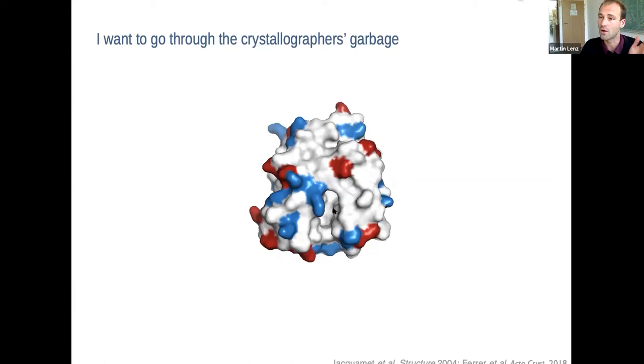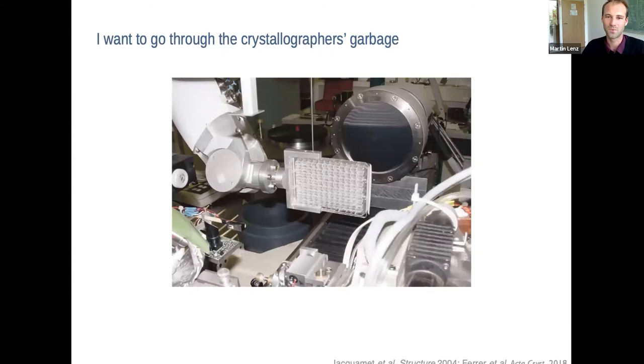And they try to crystallize them with depleting agents, salts, surfactants, relatively mild aggregation conditions, because they want to get a nice crystal. If you push them too strongly together, you get something amorphous and you don't get a very good scattering signal out of it. They do this in those 96 well plates. And most of the time, they fail. Most of the attempts to crystallize those proteins are unsuccessful, but there's a few of them that are successful, and then you put them under the X-ray beam and get a scattering picture out of it.